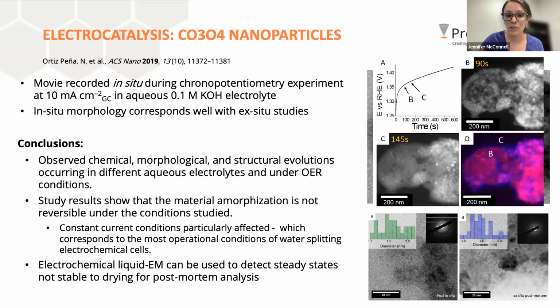They analyzed the crystalline portions of the particles. When they took the holder out, disassembled the cell and put the same chip, the same sample, back in to do further analysis at higher resolution, they noticed quite a difference in the distribution of the crystalline particles and the sizes. So drying the sample for postmortem analysis in this case was not ideal. Had they not done this experiment while in liquid, they might not have realized such a difference. Really changing the state the sample is in, even just drying it out, can really affect the results you obtain and potentially the theories that you pose.